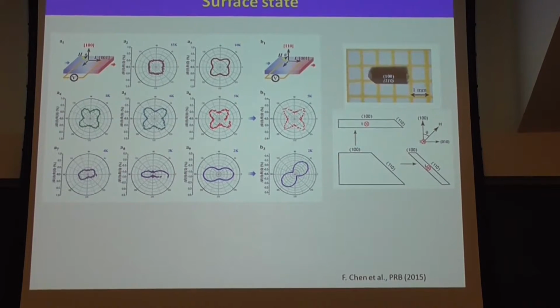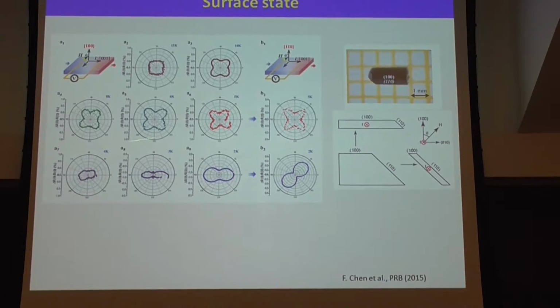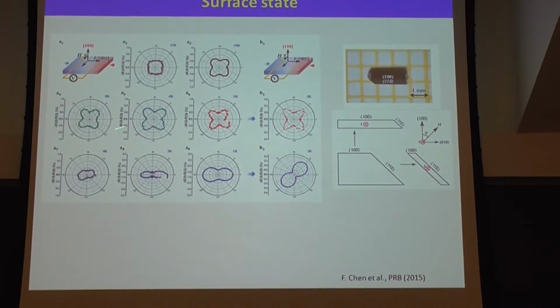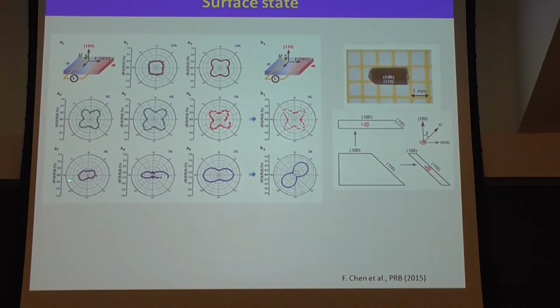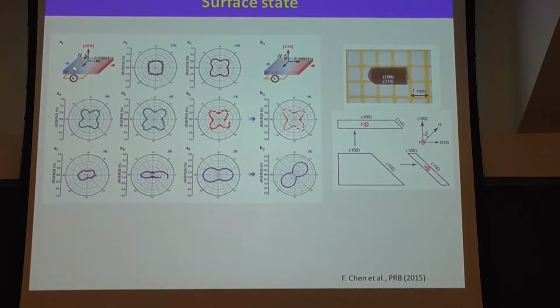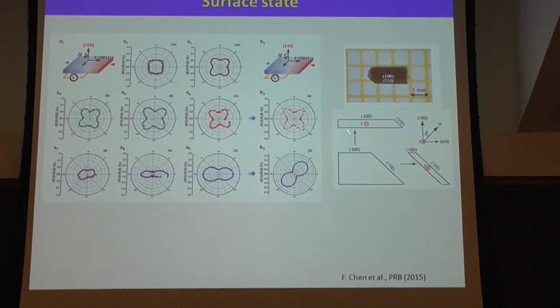this anisotropy is just fourfold symmetry, you can see. Then below 5 Kelvin, the symmetry changes to twofold. This is for the 100 surface. But if I change to the last one, the 110 surface, I also do the same thing.